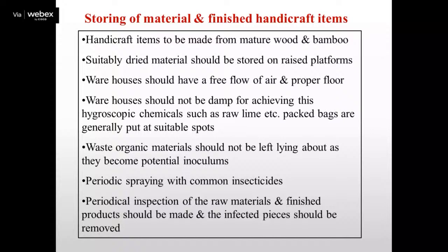Storing of the material is one of the important factors. How to store these materials and the finished handicraft items to preserve them for a long time? Handicraft items should be made from matured wood or bamboo. Suitably dried material should be stored on a raised platform. That is one of the important steps. Warehouses should have a free flow of air and a proper floor. It should not be a muddy floor, it should be a pucca floor. Warehouses should not be damp.